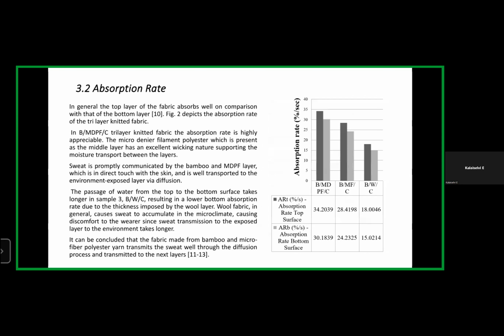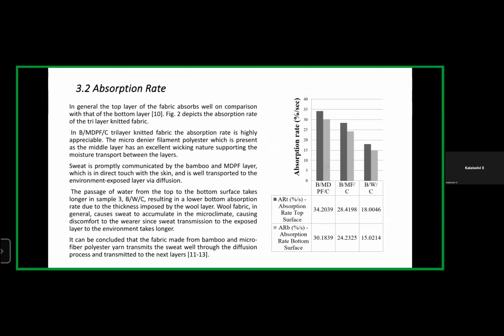Absorption rate. Compared to the absorption rate, you could see the results. The absorption rate for bamboo microdenier filament polyester has a good absorption rate, and for bamboo wool cotton, the absorption rate for the top and bottom surface is comparatively lower than that of the other two samples.